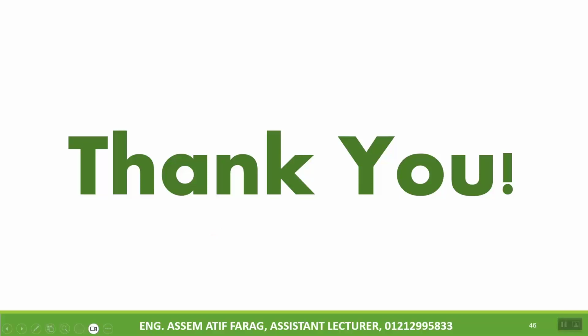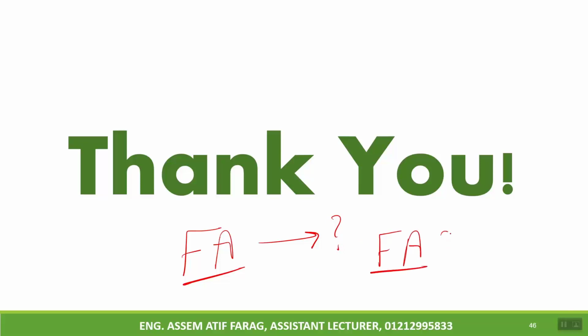This is the end of our session today. Today we talked about using fly ash in concrete and whether it is a sustainable material. We concluded that by increasing the percentage of fly ash in concrete, it reduces its service life, which may cause it to be a less sustainable option than using ordinary reinforced concrete. But in this study, we concluded that a replacement percentage of about 30% is the optimal value for using fly ash as a replacement in concrete, to consider both the environmental aspects, economic aspects, as well as social aspects.